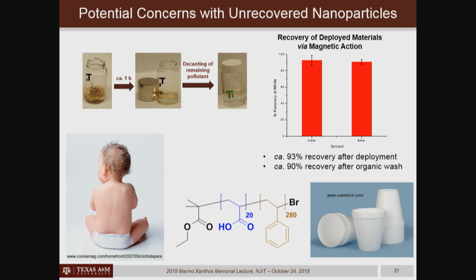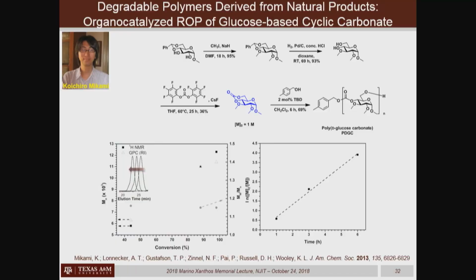So we needed some chemistry to take natural products and build them into these amphiphilic block polymer structures. And that chemistry was developed by Koichiro Mikami, who was a postdoc in the lab. And again, this is a lot of chemistry here. Let me say that the key starting material is this cyclic carbonate of glucose. So he can start with a commercially available small molecule, do a couple of chemical reactions, and access this species that then has, what's important here is this 6-membered carbonate ring, because in the presence of an alcohol and an organobase, this can undergo ring opening polymerization, and that's a chain growth polymerization, and it can be well controlled.